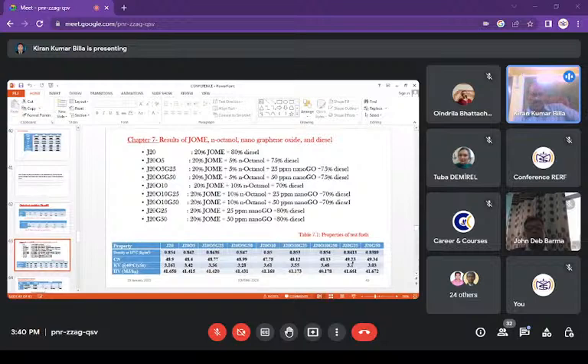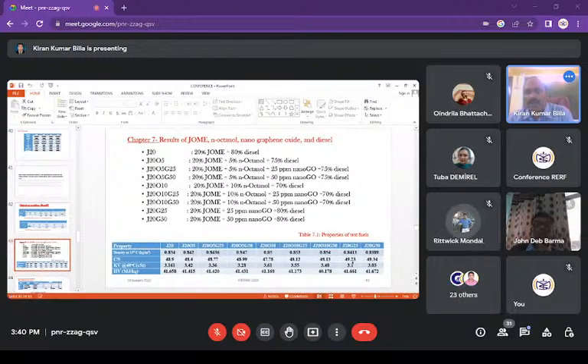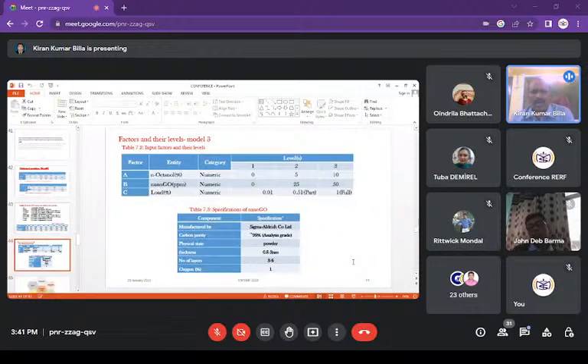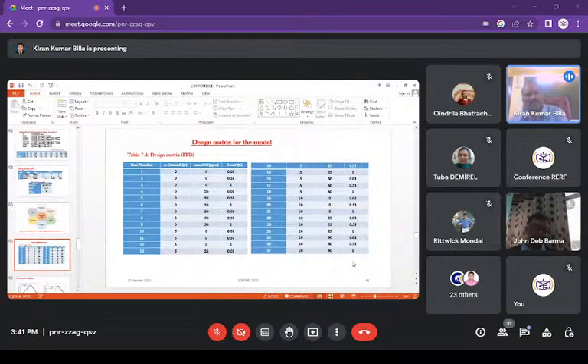Next, coming to another important experiment I have done: as I told you, using 20% Jatropha oil and 5% to 10% N-octanol, the oxygen percentage and the viscosity are getting a little bit higher than the conventional. So there are a little bit of oxygen issues and this viscosity issue. In literature I have found that using some state of the art additives like graphene oxide gives good results. So I tried this nano graphene oxide in this experiment. It is a good move, as I can say.